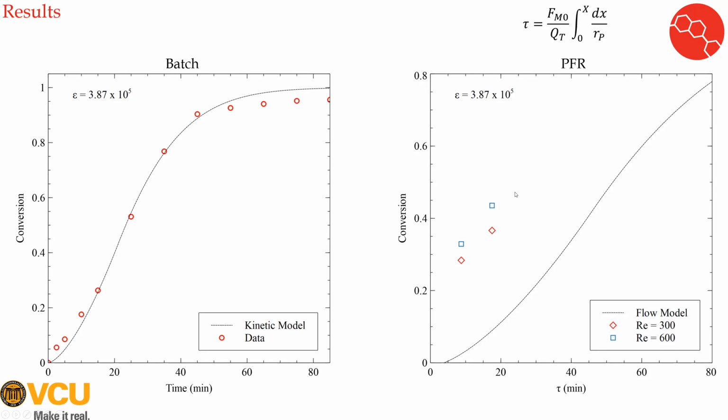What we anticipate is occurring is that we are artificially decreasing this value of epsilon in favor of forming new particles, and we're getting a much higher number of particles at a smaller size. So hopefully we can use this information to get much faster conversion for a given time that we might have to wait to run experiments, and thus facilitate the quick screening of new adhesive formulations, as well as possibly control the particle size.